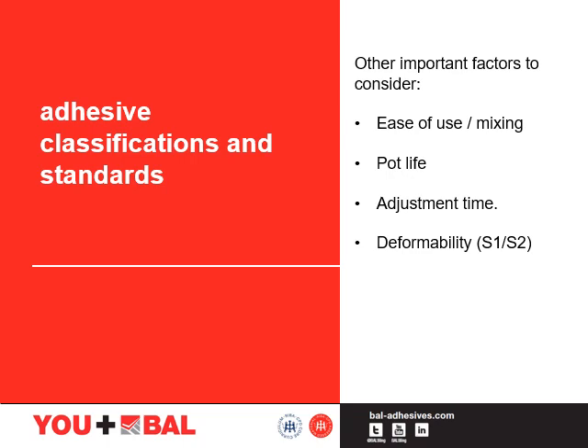The first three are not tested for in accordance with the EN 12004 requirements, but are important to the end user and assist in providing an adhesive which is easy to mix and apply with a good working time. This allows for adjustment of pre-bonded tiles within a given time. BS EN 12004-2 has a test to measure for transverse deformation of tile adhesives. This gives us S1, which is deformable, and S2, which is highly deformable.